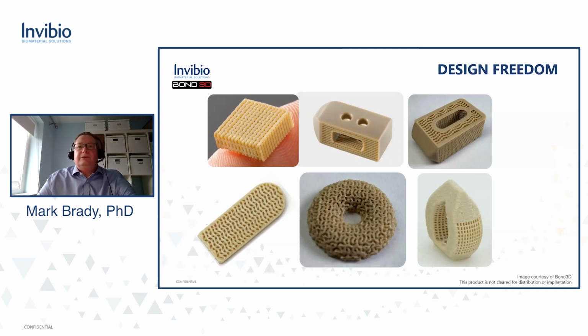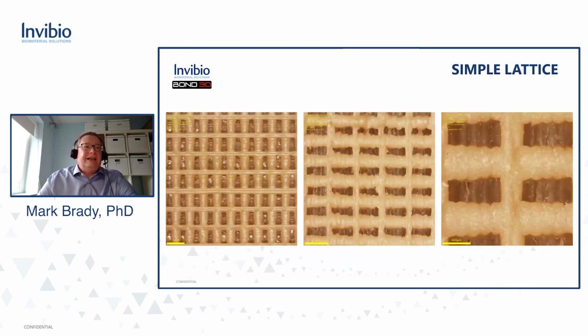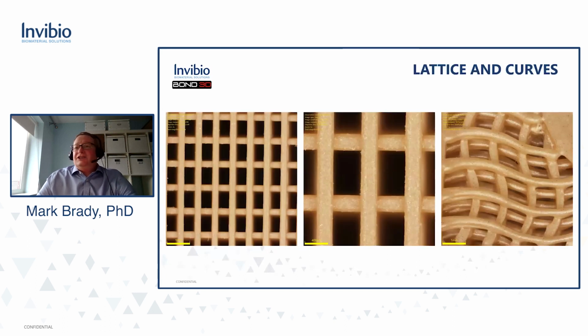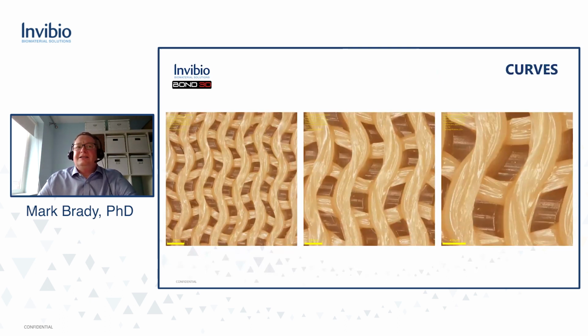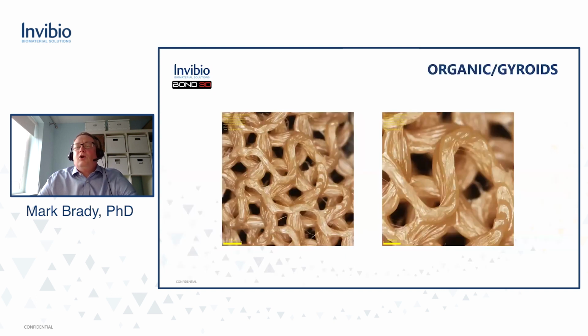So you can achieve simple lattices like you see here on some of these demonstrator parts. Taking a closer look at some of those lattices, just alternating and changing up the spacing and the sizing of those pores, changing towards curved tracks, which allow a more organic look to our parts, and just looking at a little bit more detail here, just really how controllable and consistent the features are that can be achieved as we move into porous structures, all the way to even more organic forms and gyroids that really start to take on the appearance of more trabecular looking features.